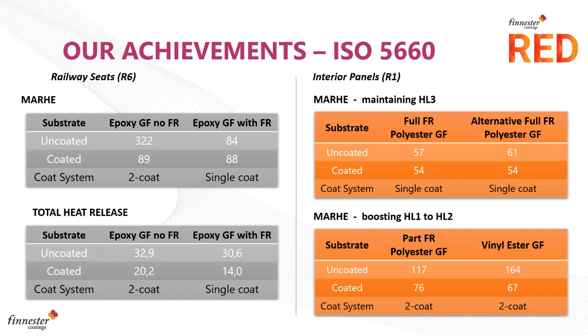But also we can take a partly fire retardant polyester glass fiber. If you have an uncoated glass fiber system, and this is giving you somewhere in the region of 117 MARHE, then with a two-coat application, you can bring that down into a hazard level 2. So giving you different examples of different types of substrates that we've used and demonstrating with consistent data how we can get to meeting these fire requirements.